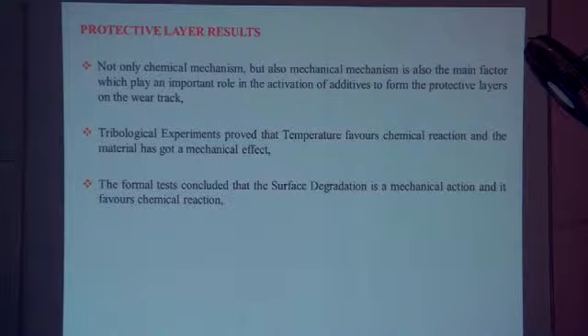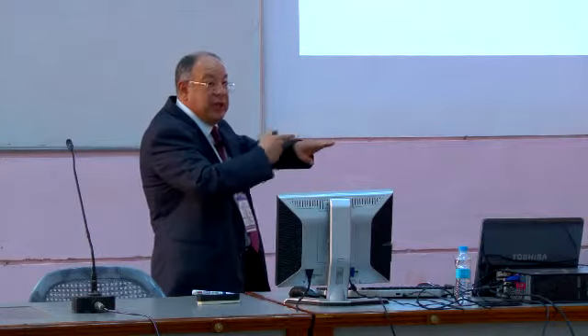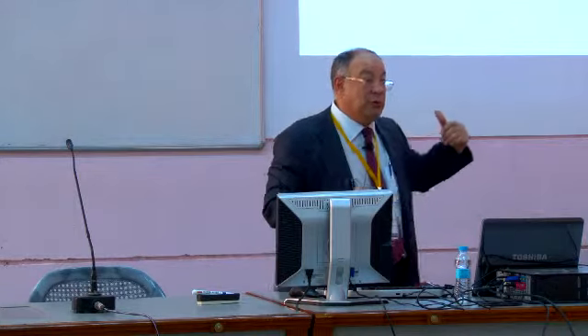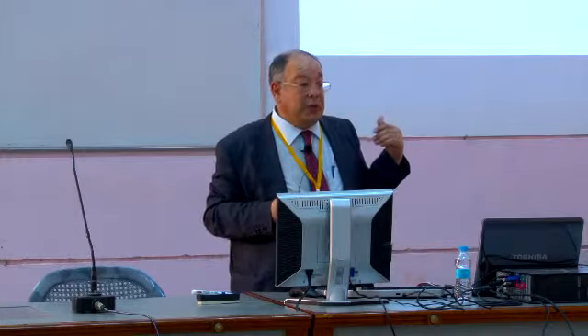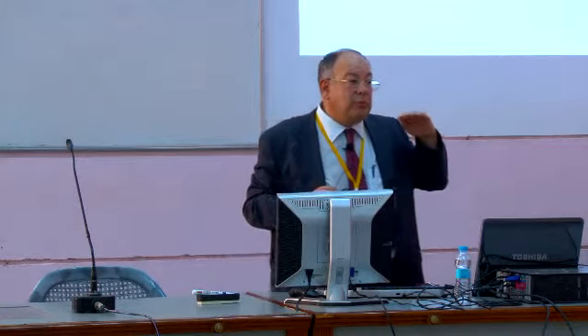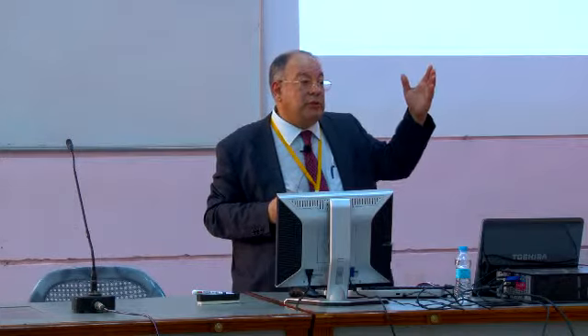Formal tests concluded that surface degradation is a mechanical action. The surface must be degraded slightly to form additive layers. I don't put this in the slide because it takes a long time, I'd have to talk until evening. Just what I mentioned, we did some small dry tests, short dry tests of 1-2 minutes, under the same conditions.